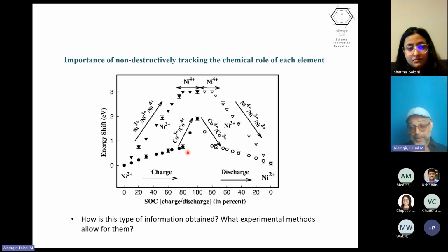So lithium is the trigger in this case. The lithium is in fact being extracted, and it is safe to assume that lithium itself is in +1 oxidation state the entire time in the cathode material. Whatever lithium remains is always at +1 oxidation state, nominally speaking. But for the oxygen information, one can assume that it is staying at oxygen 2-, but maybe it isn't. And that is missing from here.